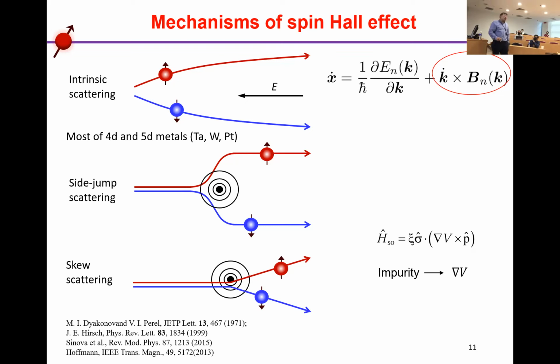The mechanism of the spin Hall effect, there are two kinds. One is the intrinsic mechanism, based on the Berry curvature, which induces a monopole magnetic field, which separates electrons with spin up and spin down in the transverse directions. Another one is the extrinsic effect. We call it side-jump scattering and skew scattering. This is when you dope some elements or impurities in the materials, which will generate an electric field gradient and cause spin-dependent scatterings.